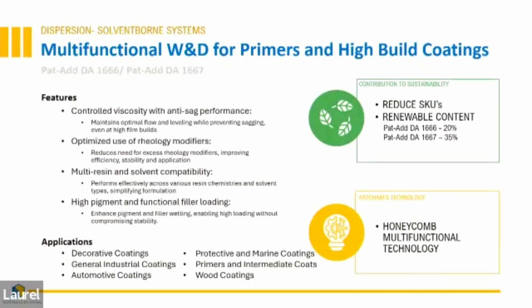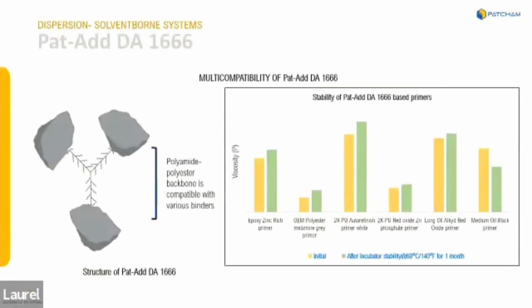So we use these dispersion stabilizing additives to enable the manufacturing and the production of these types of particulate dispersions in the system. And what we're going to look at is a particular dispersant system that is capable of self-structuring by itself. So in addition to dispersing these particles, it can associate with itself to provide then stability for prevention of separation due to gravitational forces and the density differences of the materials in the system.